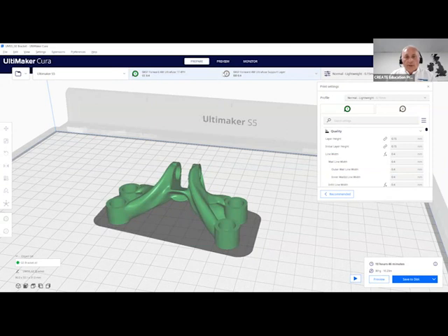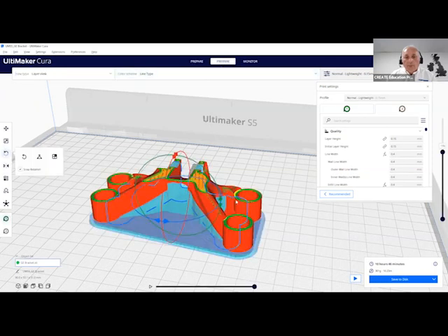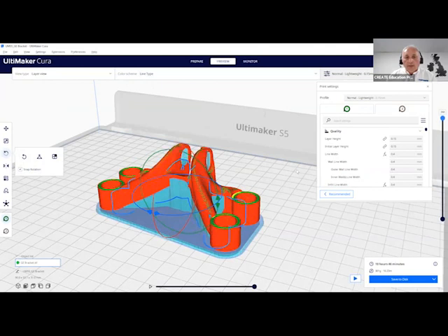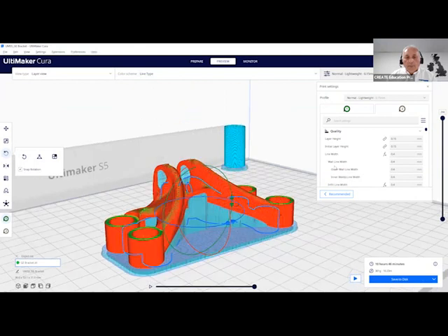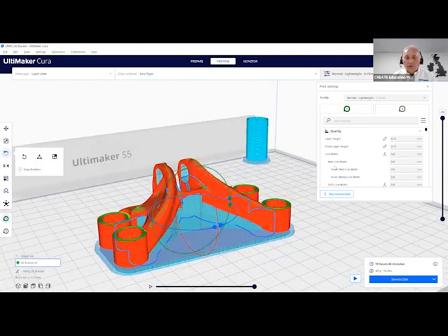And when you slice this now, because we've got these material profiles loaded in, when I go to the preview and click on the model, what hopefully you should be able to see is a very faint blue outline there, which represents the size of the model as it was brought into Cura. But notice the sliced part size is substantially different, and this is the scaling factor that's automatically applied to the part that accounts for the shrinkage that's going to occur when it goes through post-processing. So in this case, this material shrinks 19% in X and Y, but 25% in Z, so it's non-uniform. So you need to apply a non-uniform scaling factor to be successful with this.